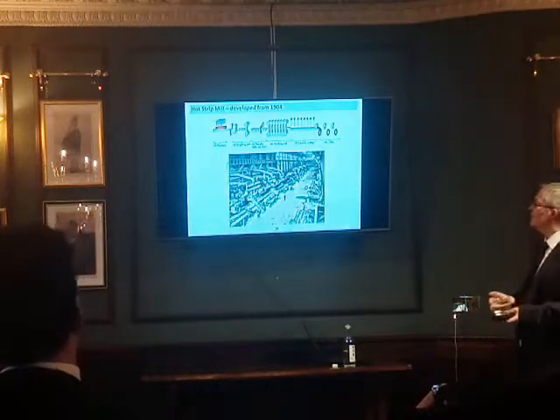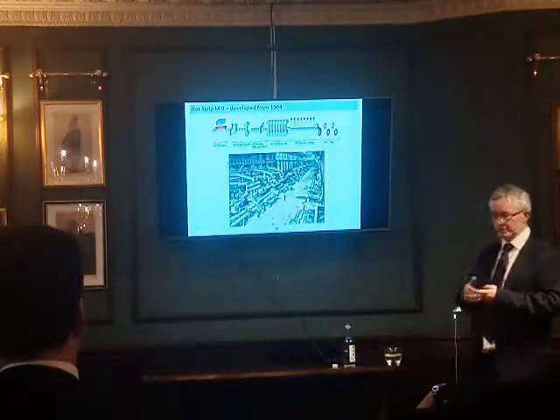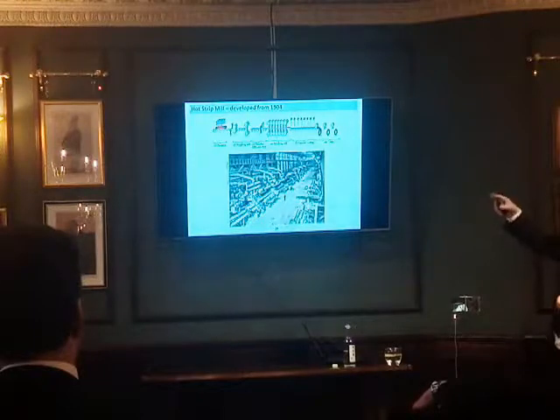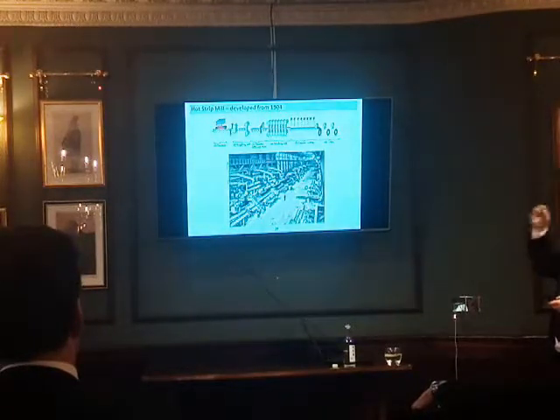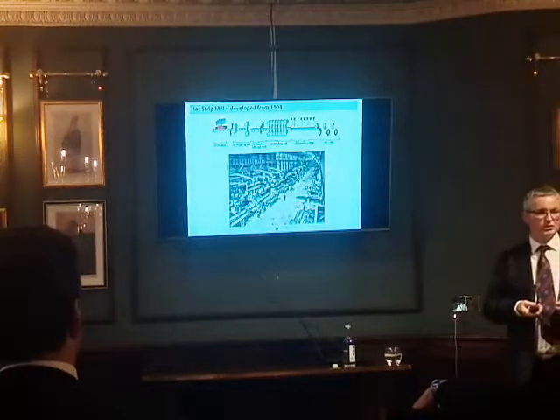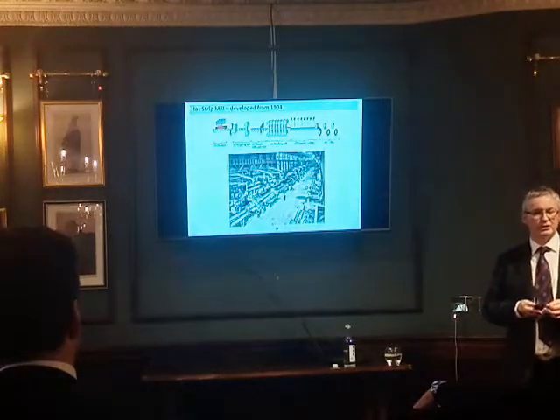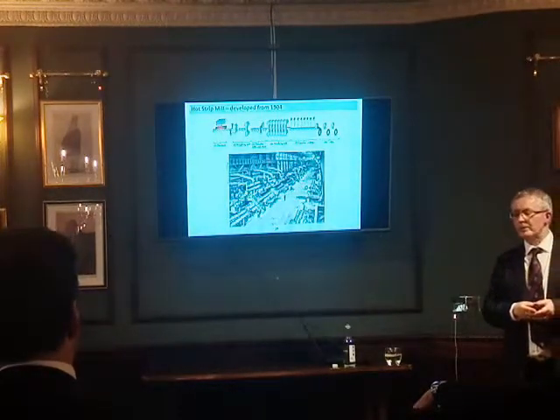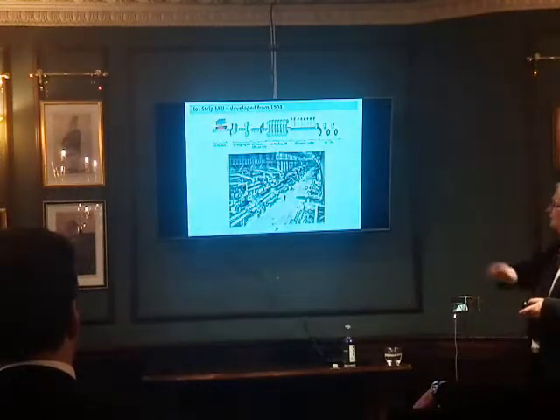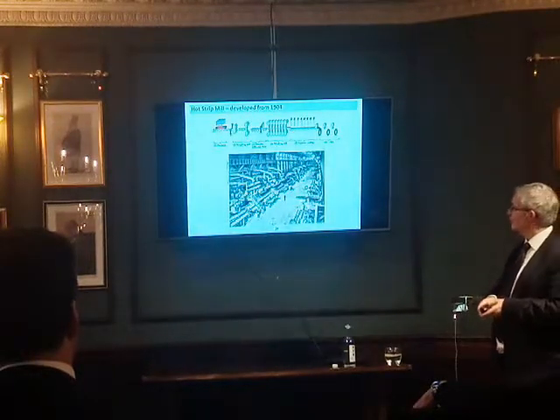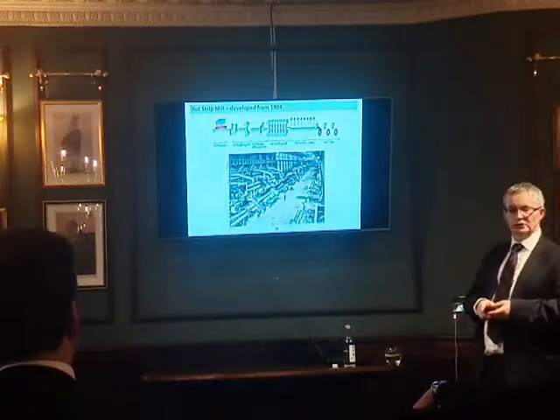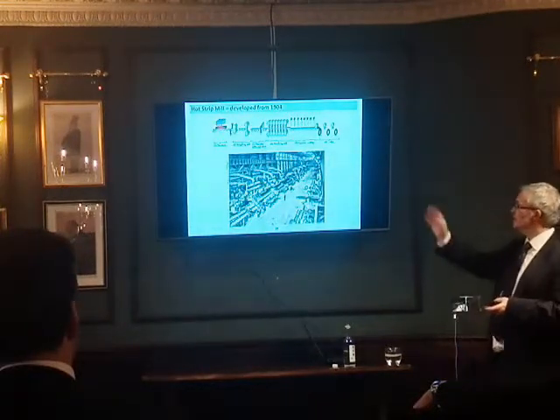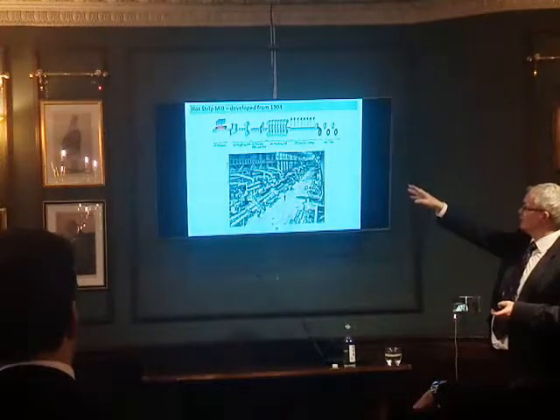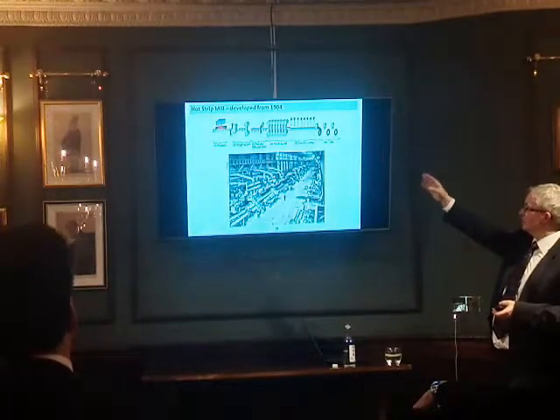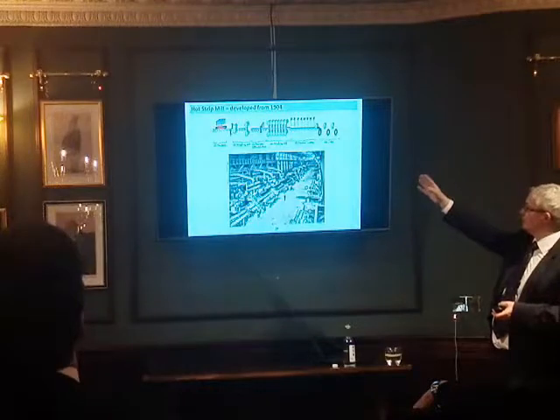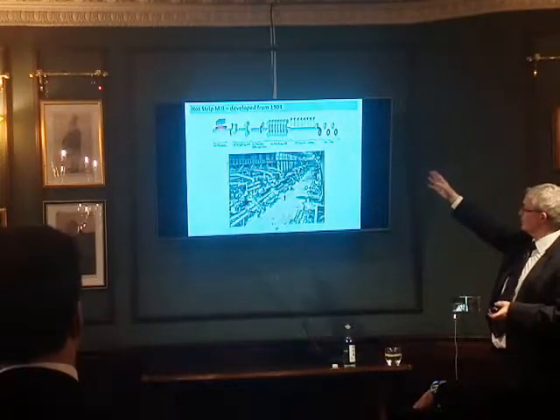And in the early, so what happened to these ingots? Well, we didn't quite jump straight into hot strip mills, but I wanted to put a diagram in of a hot strip mill somewhere. This is a very early hot strip mill at Sparrows Point in the USA, probably jumping ahead to the 1930s, rather than back in 1900. It's a massively long building, probably half a mile or more long, some of them even longer than that. So you take the ingots, you break it down, you go through a roughing mill into transfers and so on, then through a finishing mill, through cooling, and then into coiling.